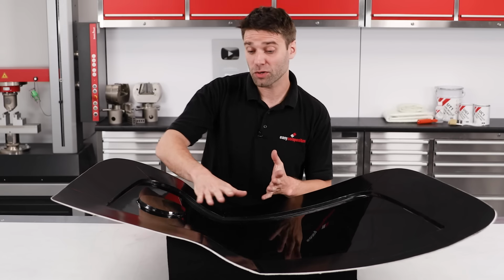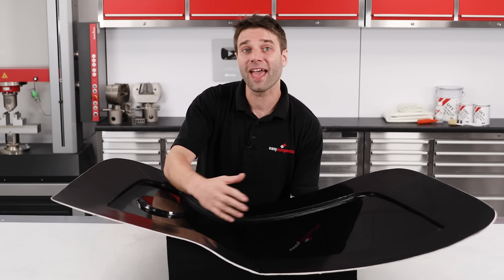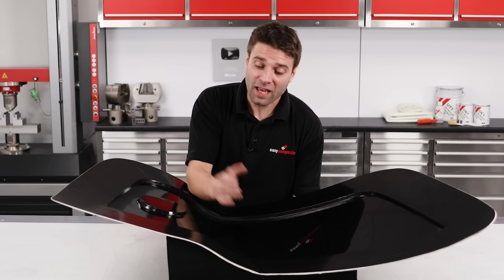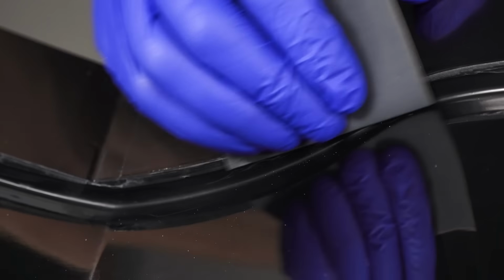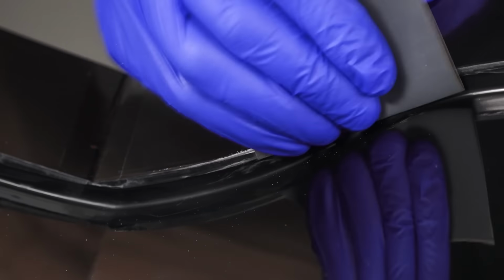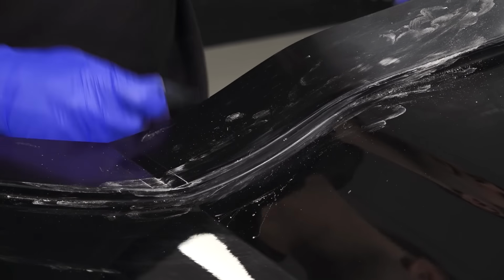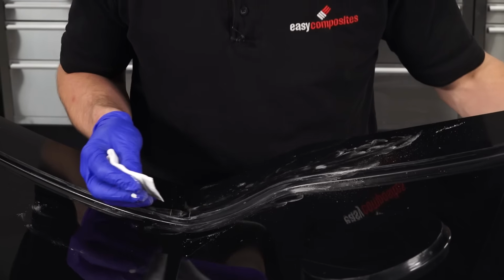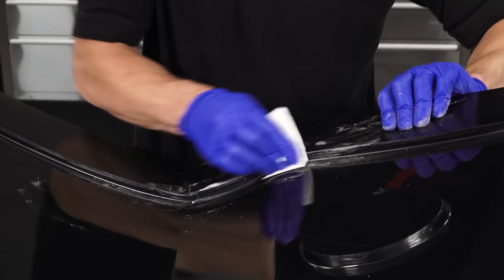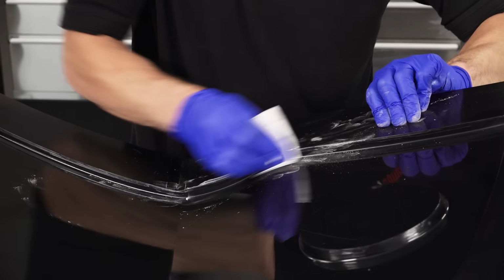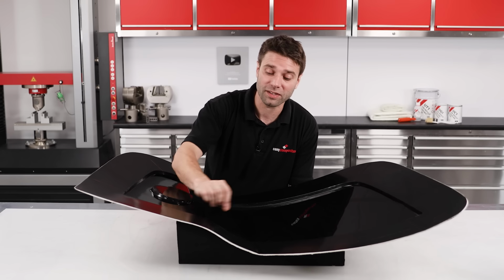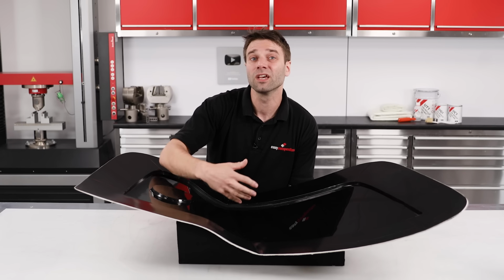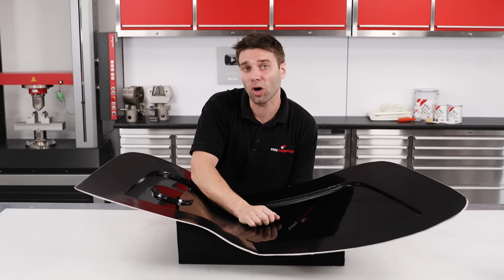The next thing to check on your mould is if there is any repair or refinishing work needed. It's not uncommon to get small raised nibs like this, particularly where the filleting wax has been used. If you do find any blemishes like this, they should be sanded smooth with 800 followed by 1200 grit abrasive and then polished in with some NW1 polishing compound. If you were to just leave these, there is a risk that when you come to mould the part, it's going to mechanically lock against them and could chip or damage your mould.